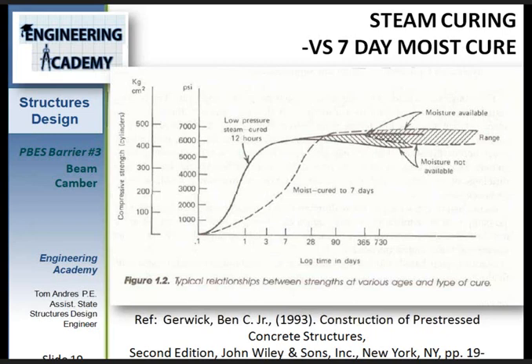I apologize for this slide. It's not a really good photo, but it does show the strength gain. You can see the vertical axis, again, concrete strength, and then log time in the horizontal direction here. Strength gain can be achieved by using steam curing with less additional cement added to achieve 1 to 2 day bed cycle times. This allows the actual mixes used by precasters to behave closer to the theoretical mixes assumed during design. Also, the controlled temperatures, one would think, would likely make camber predictability and repeatability much, much better, right?